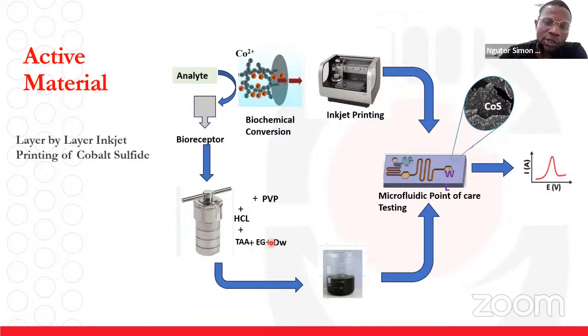Then we use ethylene glycol. Because of its double OH, I think from literature, it has more enhanced properties than even ethanol. And then we add it to distilled water. We were able to print this material and the cobalt sulfide, of which this work is not yet published.